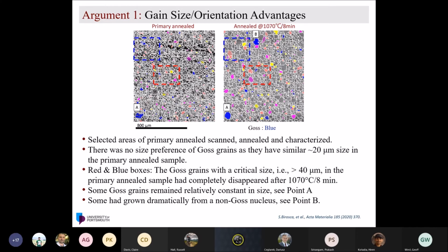So we tried another set of experiments to find out if we can prove that microstructurally. We did a quasi in situ part. We selected some area, not using an indenter, as it might cause some recrystallization during the indentation, so we used a marker. We have the primary anneal, we did the EBSD, then we annealed it at 1070 for 8 minutes, and looked at exactly the same area. However, we were careful about how much we go further, just in case. We just went by a few micrometers, in case we're missing some information in between.